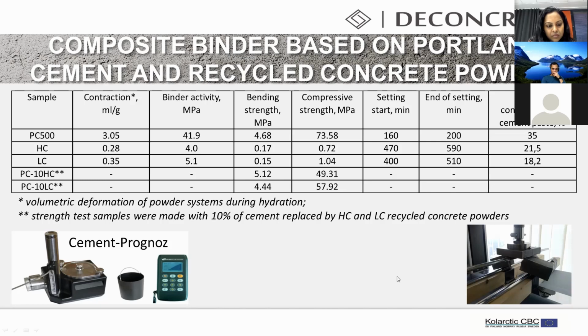And also, as you can see, if we use only our powders from lightweight and heavy concrete, they have very different setting start and end of setting compared to Portland cement. And normal consistency also differs from the cement paste. So this explains the relatively low compressive strength compared to Portland cement.